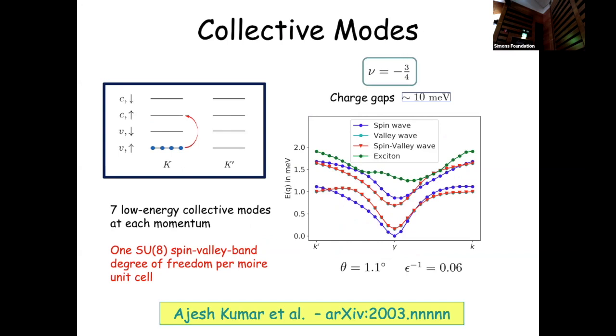Here's a calculation for an insulating state. I think it might not be very different for a metallic state, of collective excitations in this system. This is actually an example of a quantum anomalous Hall state with 1 valley filled for 1 spin. So there are a bunch of collective modes actually corresponding to transitions between the occupied states and all of the empty states. And the very surprising thing about this, I'm not showing you here the band excitations in this insulating state, which have an energy of about 12 meV. These are only collective modes.